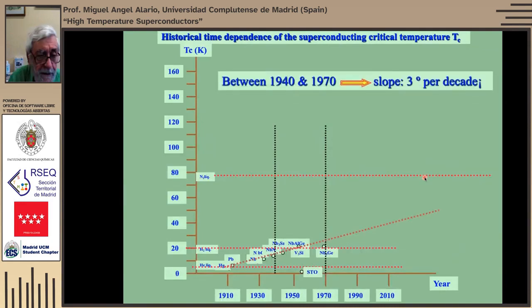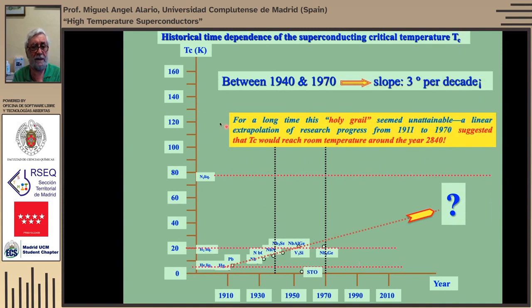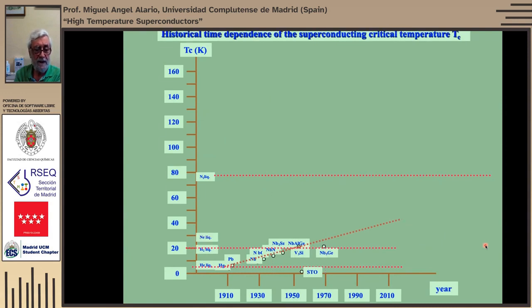Anyway, we keep on going, and from 1940 to 1970, the slope of the plot is about 3 degrees every 10 years, which is, of course, a very, very small slope. So when will we get to room temperature, which is important for applications? In 1970, somebody, I forgot the name, suggested by extrapolation of TC that we would reach room temperature superconductivity in 2840, which is very funny. It is not good for the people working in the field. Anyway, whenever you make predictions, often you are wrong.